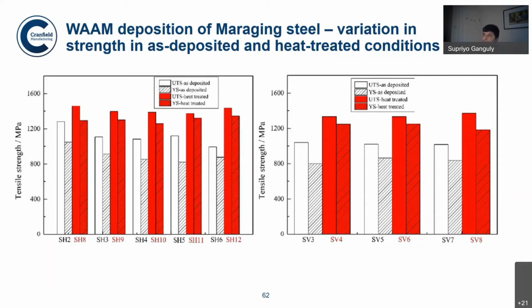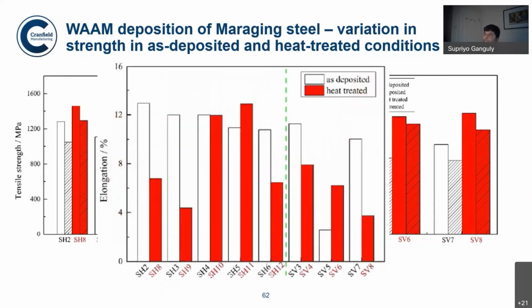So in as deposited and heat treated condition, this alloy fails to achieve the maximum or optimum strength. In this particular graph we are showing the elongation, and it can be seen that with the heat treatment the elongations are primarily reduced, or the area under the tensile curve is reduced.